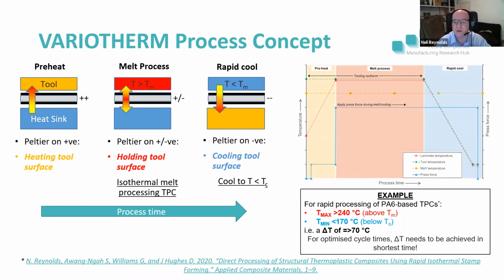On the right-hand side, you can see a typical process breakdown for this variothermal process, where we have three key stages. We have a preheat stage on the left, a melt process stage, and a rapid cool. Looking at the schematic graph of temperature versus time, you can see there's a rapid increase in temperature, a hold during the melt process, and then a rapid cool.